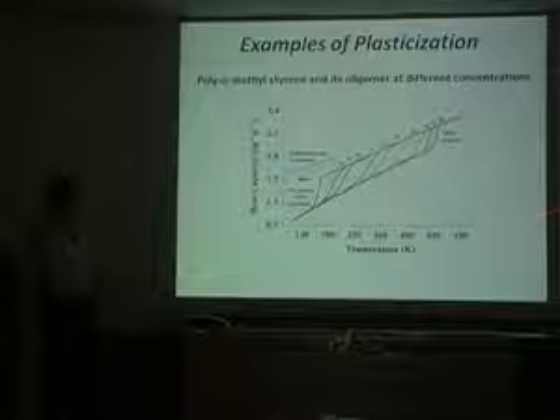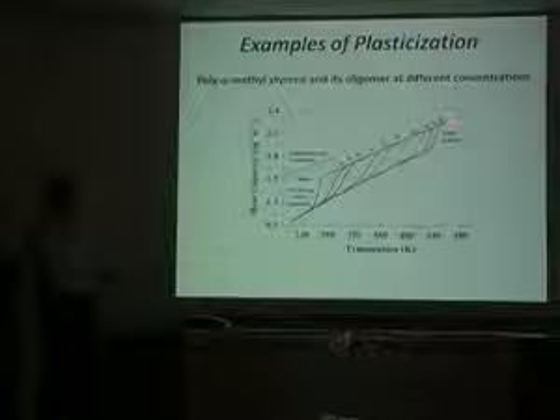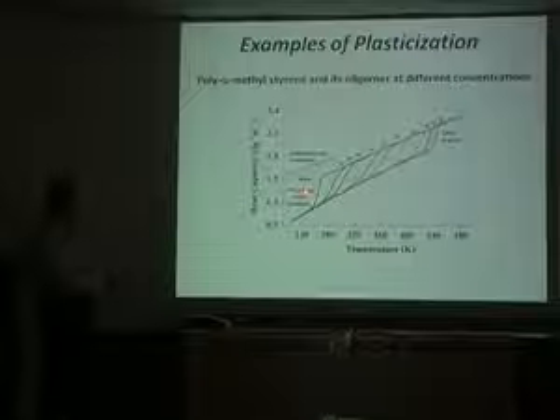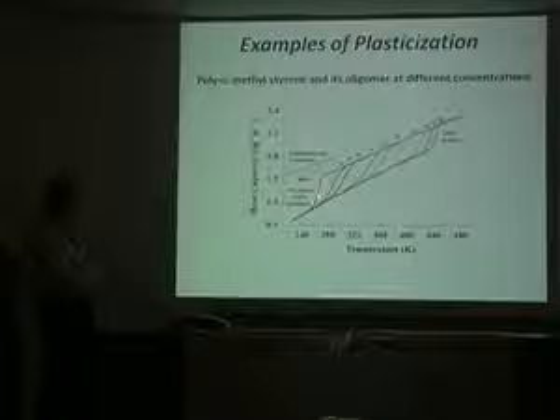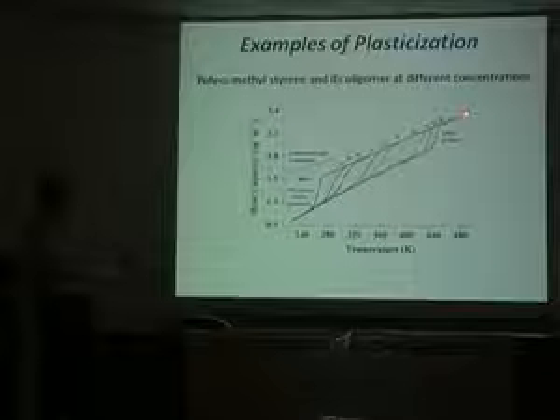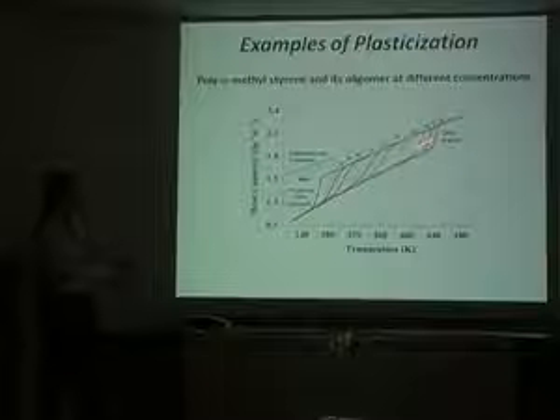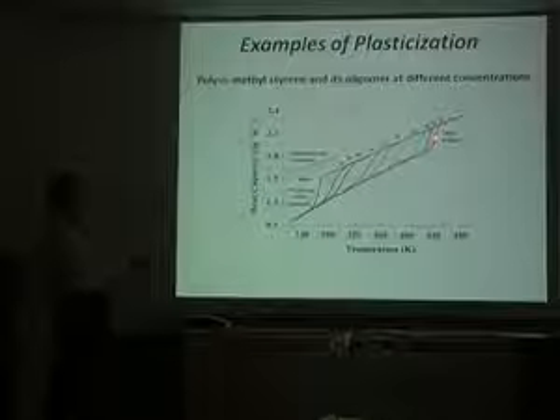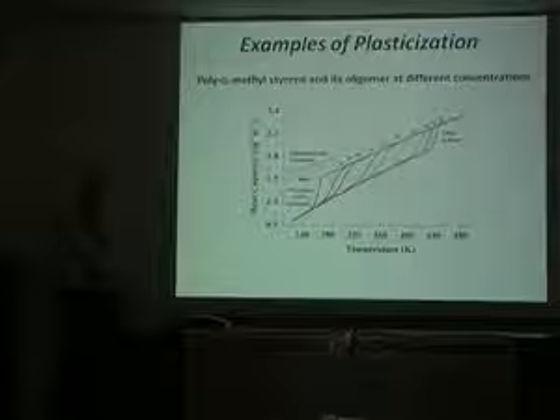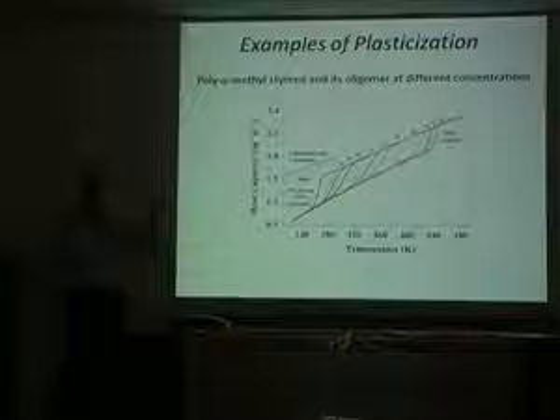This is a poly(alpha-methylstyrene) polymer, the heat capacity versus temperature at different concentrations. Here's 100% polymer, so you see Tg is up here, greater than 440 degrees. And this is the pentamer down here; the Tg is only about 260 degrees or something like that. And it's interesting, the equilibrium curve is independent of concentration, but you don't have to worry about that for now. I can actually imagine putting in a little bit of this, and I'd change Tg. And if this were volatile, which it's not that volatile, I could just change pressure, and I could jump the glass transition.